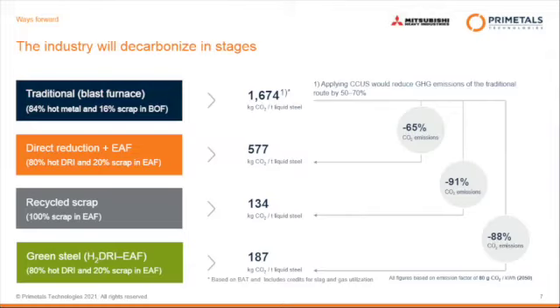The most promising route would be the recycling route. So, just melting the scrap, 100% scrap. And if we consider a low grid factor on scope 2, you see 80 gram CO2 per kilowatt hour, which is in the EU already targeted for 2030. It can be as low as 130 kilogram of CO2 only, so minus 90% over the blast furnace route.